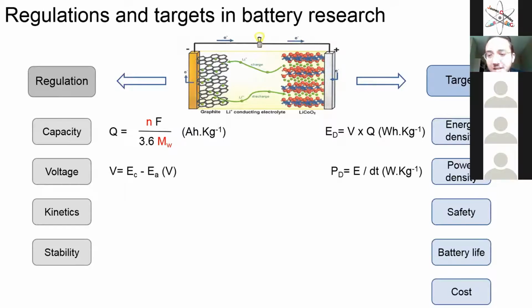So in order to reach these targets, we have the regulations. We should look for our materials, in general, not only organic materials, we should look for electrode materials that can provide high capacity. And how is that? We look for electrode materials that have a low molecular weight and can exchange as many electrons as possible. Because here we have the formula on the left, based on the number of electrons exchanged and the molecular weight, we can calculate the capacity, which can be expressed in ampere hour per kilogram. Then you have the voltage, which is the difference in potential between the cathode and the anode. So the potential of the cathode should be as high as possible, and the potential of the anode should be as low as possible. By doing this, you can maximize the voltage, and then this voltage and capacity will give direct access to the energy density.